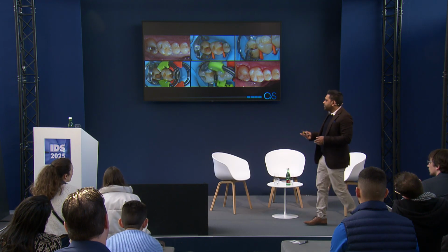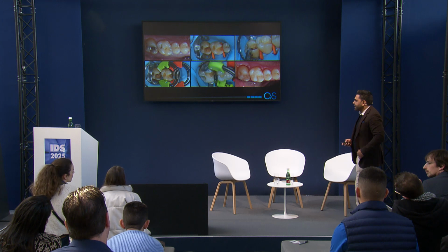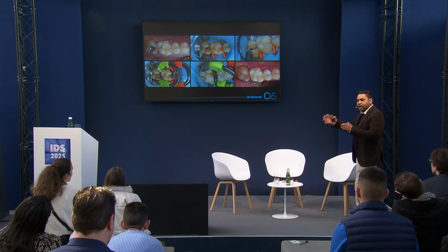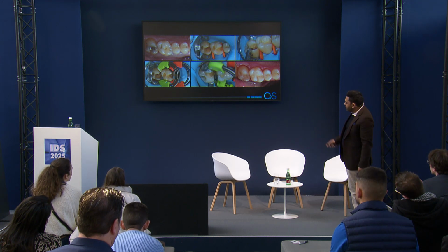That effectively means that we get reduced flash, much less finishing of our restoration. The other big benefit of the matrix system is that it has anatomically shaped matrix bands, and they have a little lip at the end. So if we're doing deep marginal elevation, we get a really predictable seal. So I'm very confident that we get a nice mesial marginal ridge. And that moves me on to my next point.